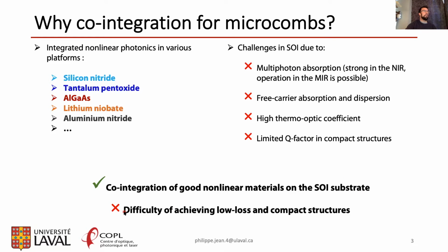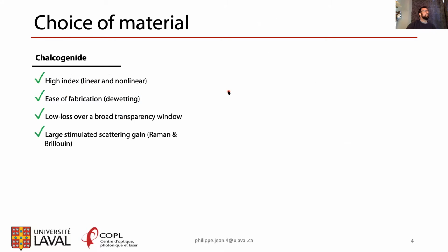This is a topic that has already been studied to a certain extent, but in general, it's tricky to achieve low loss and compact structures that are required for efficient nonlinear photonics. So the choice of material for this work is chalcogenide. The reason for that is that they present high linear and nonlinear index. Only Chi3, not Chi2, of course, because this is a glass, so it's amorphous.